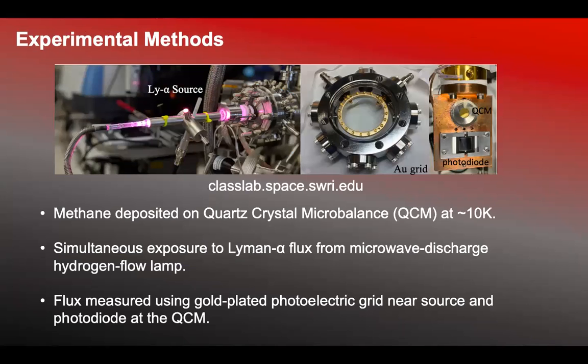So in the laboratory, what we do is we have another chamber. This is in a different laboratory from the one that the SwRI is in, where within the chamber, it's brought down to very high vacuum, and a very small amount of methane is introduced into the chamber and frozen down to 10 Kelvin, very, very cold. And this is meant to specifically simulate what is going on at Charon, because that is the estimated surface temperature toward the poles of Charon during the time period of this methane deposition. All right.